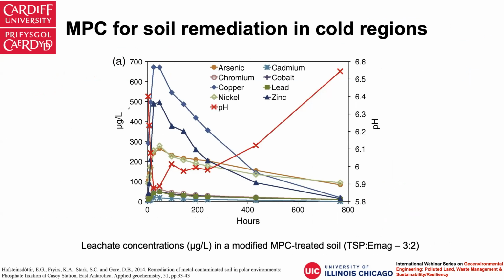So I'll just pick some examples of using the modified MPC for soil remediation. This graph is extracted from one of the Antarctic studies of using modified MPC for contaminated soil remediation. Because it's an Antarctic soil, the temperature can be as low as minus 20 degrees C. Under such extremely low temperatures, normal cementitious materials don't work, because most cementitious materials, particularly Portland cement, only react at a certain rate at ambient or higher temperatures, because the reaction is exothermic. If the temperature is extremely low, the hydration will stop.